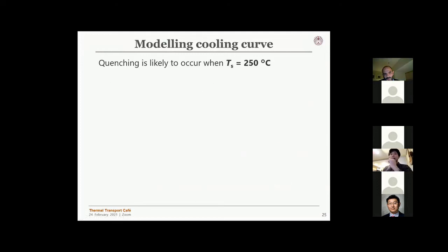So then I'd like to move on to the modeling of the cooling curve. From our experiment, which is still a single droplet impingement experiment, not exactly spray cooling, we can infer that quenching is likely to happen when the surface contact temperature is about 250 degrees Celsius. There's still a question why 250, but we'll leave that there.